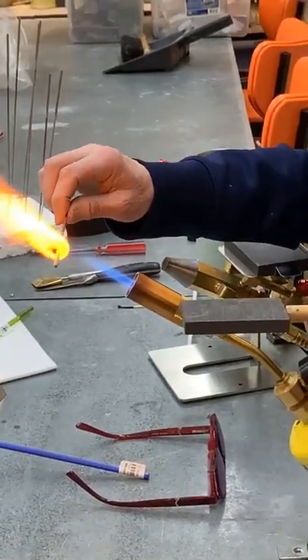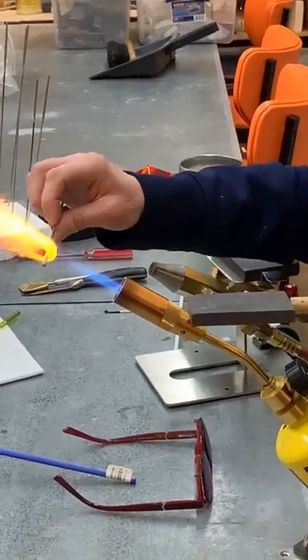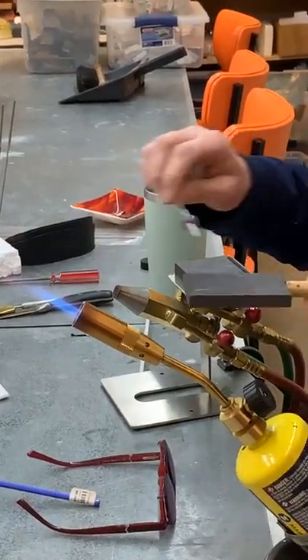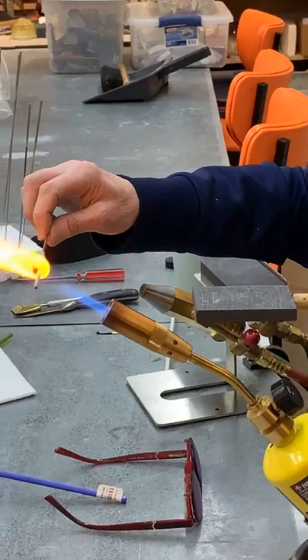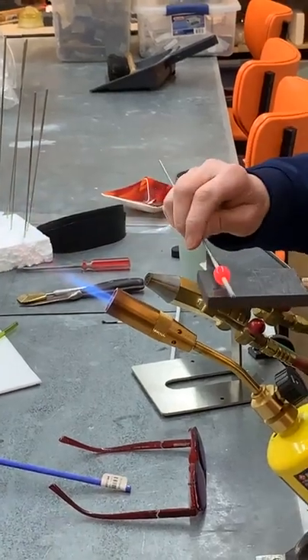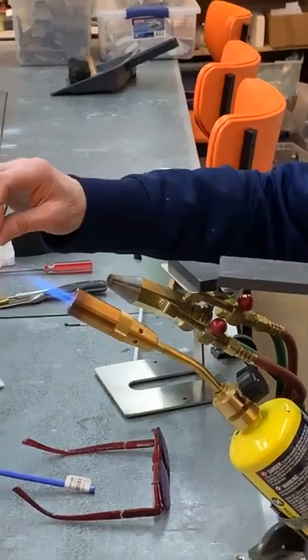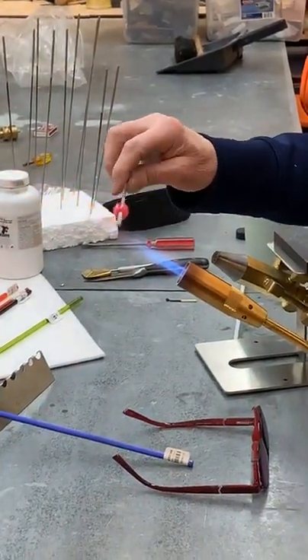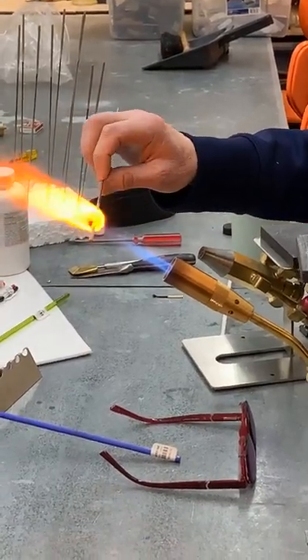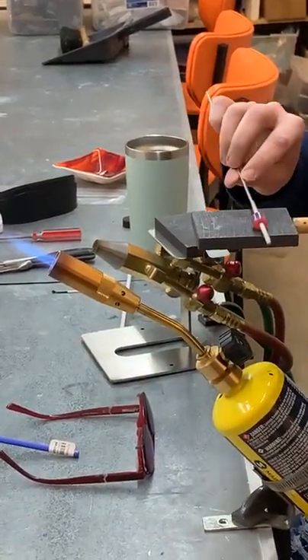Now what I want to do is just get this melted. You can see how ropey it still looks — that's telling me it's still pretty stiff because it's holding that ropey texture. Once you stay in there you'll see those ribs start to fill in a little bit. Now it's getting soft enough that I probably can do something with it. It's very gentle — you get the glass soft and then you use your graphite paddle as sort of a suggestion to the glass as to what you want it to do. If I push and smash while it's still stiff I'll just break the bead loose.